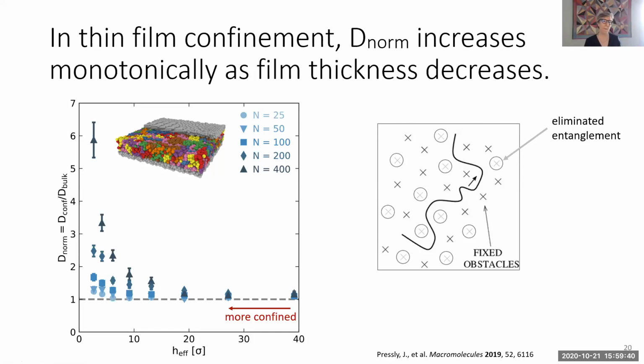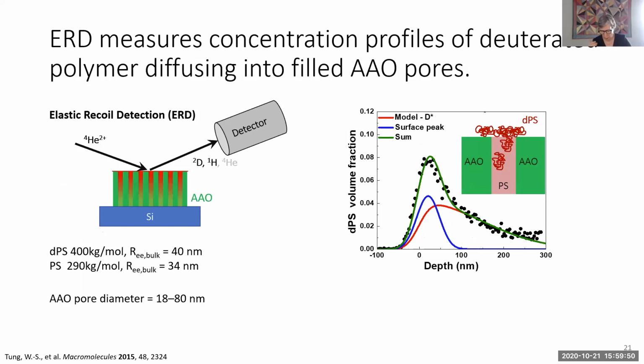All right. Now I'm going to take a little break from the simulations, and I'm going to show you the experiments. And we actually did these experiments first. So we took an AAO, an anodized aluminum oxide template with these nanoscale pores. We filled it up with polystyrene. Then we put deuterated polystyrene on the top, and we let the deuterated polystyrene diffuse into the pores. And in doing that, we can get a concentration profile. So we measure the concentration profile using elastic recoil detection, which is an ion beam method that can tell you how deep inside your sample is the deuterium. And so this is a concentration profile of the deuterated polystyrene as a function of depth.